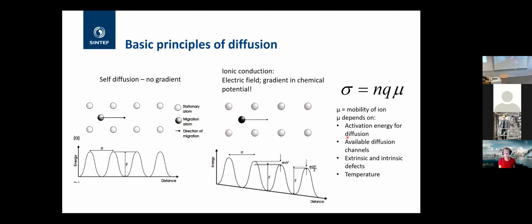You also have some extrinsic and intrinsic defects in materials, which will also affect the conductivity, and of course the temperature. However, temperature in lithium-ion batteries, at least ideally, should be operated at about 20 to 25 degrees, because higher and lower temperatures will have a great effect on the liquid electrolyte.